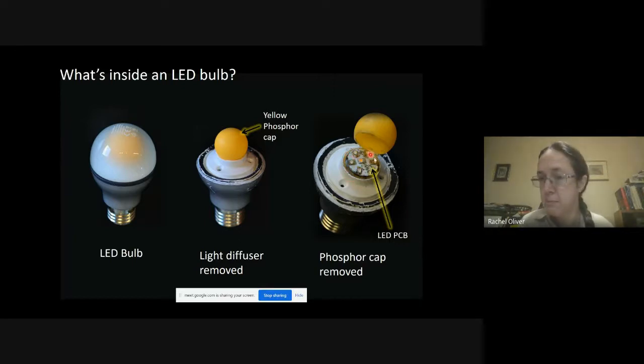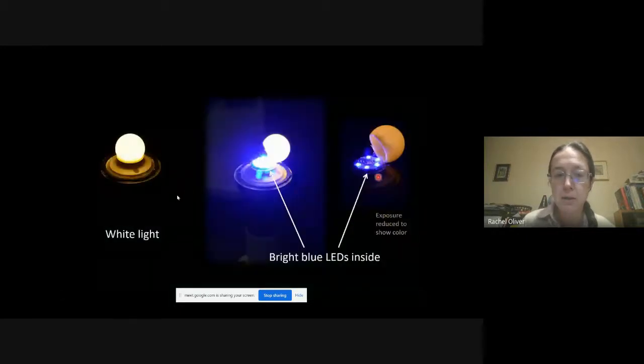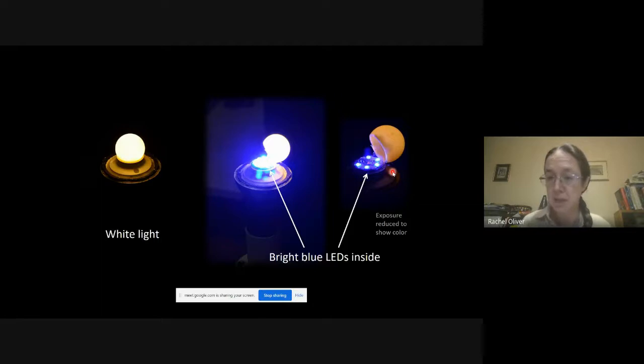There are about 5 or 6 on this particular printed circuit board. And with the LEDs on, we can see that the bulb gives white light, but underneath that phosphor cap, we can see the LEDs themselves emit blue light. And the blue light is absorbed by the phosphor, and some of it is re-emitted as yellow light. So we have this transition from blue to yellow, and the blue and yellow light combine to give at least the appearance of white. And in more sophisticated bulbs, the phosphor might give out also red and green light to give a more complete white hue.